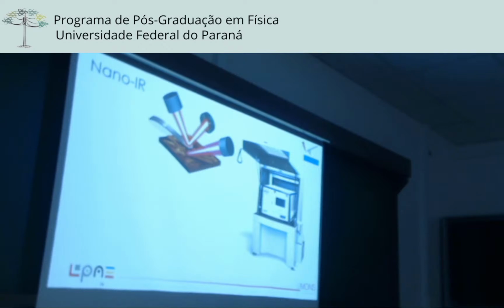And soon also we have the nano-infrared, which means that sitting on a pixel, we can start to record one spectrum and say, okay, for instance, this is the blend of polystyrene in orange and in green polyethylene. And you can either make an image at a given frequency, and if we have some highlights, it means a recognized compound, or we sit on one pixel and record the spectrum, compare it with a database, and identify the compound.